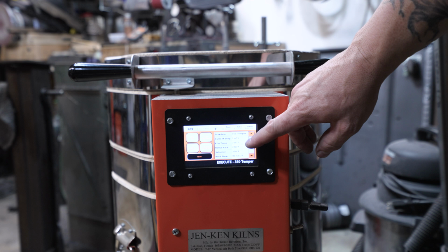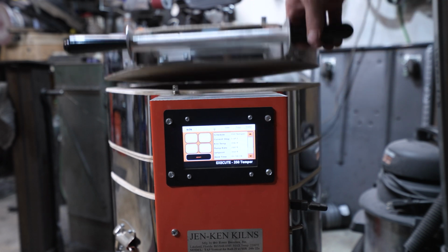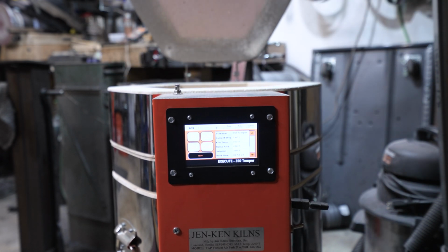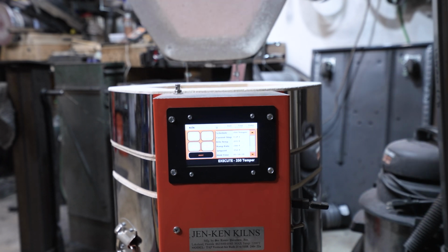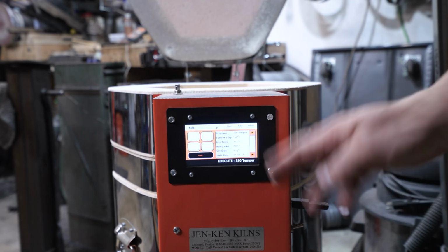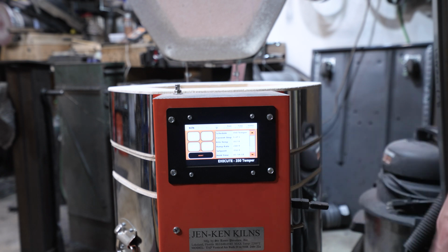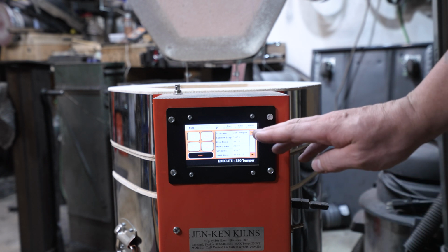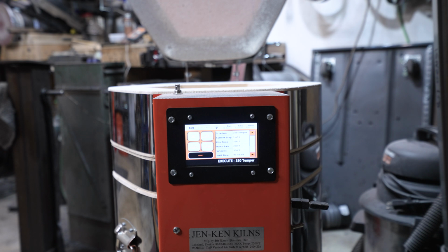But you can see right now that it's hopping up to 357 degrees. So I'll open this back up and let some of the heat out so it'll drop back down. So what I want to do is get it to where it sticks at about between 350 and 355, and then I can just let it go. I don't have to worry about it anymore. But most likely I just haven't set the schedule up correctly. The ramp speed's probably off something, but I'll get it figured out in the future. But for now, I just kind of watch this for the first little bit until everything equalizes.